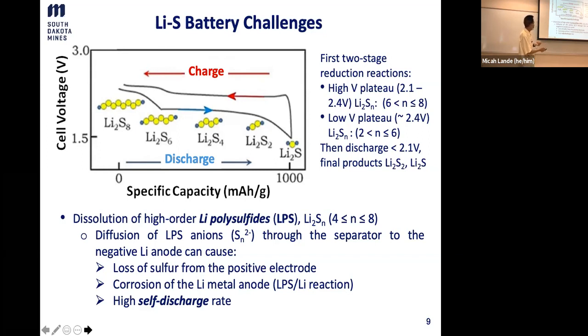What's the problem? The problem is that those polysulfides dissolve into the electrolyte, especially the higher-order ones, and when that happens, the polysulfide ions diffuse to the negative lithium anode. So why is that bad? The reason it's bad is that you lose the sulfur in the first place, right? It shouldn't move. It moved to the other side, and then it corrodes the lithium metal, which is not a good thing. And it creates self-discharge. This is another battery term.